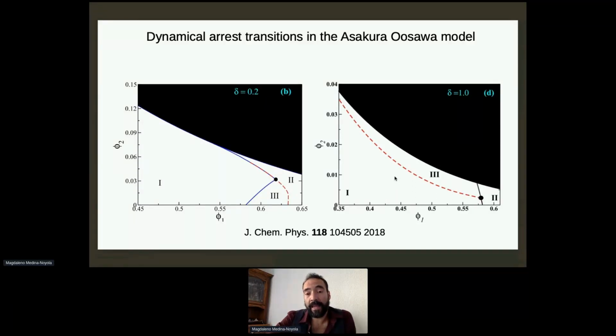For this kind of system, the theory also predicts the existence of two kinds of arrested states. One in which only the colloidal species arrest, but more interestingly, this region at which, if one fixes the concentration of colloidal particles and increases the polymers at fixed volume fraction, which is more or less a representation, of course at higher volume fraction, of Marco's experiment on NIPAM particles, there is a transition at which the polymer is predicted to undergo dynamical arrest.